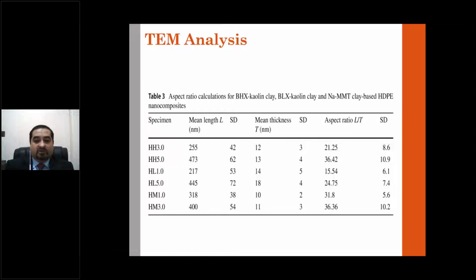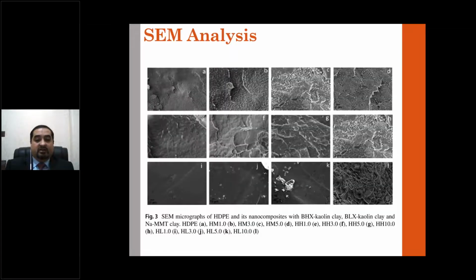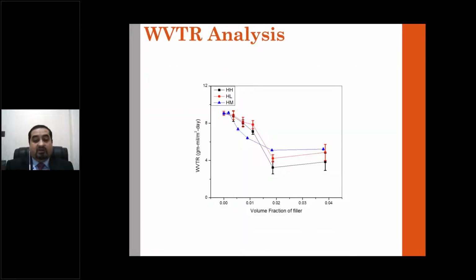Now, one of the things that you need to understand is that in terms of kaolin, we were not able to separate out individual layers, but there was a combination of layers present in the form of an aggregate. These aspect ratios basically represent the overall dimensions of those aggregates. SEM results also showed us good dispersion and distribution, and only at very high weight percentages did we get a few agglomerates and a few phase separations present within our material.